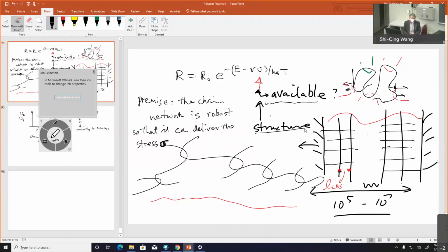So we know we need a high enough molecular weight. We can even throw a word called entanglement there, but it really says little about what entanglement does. I claim here that this chain network is what enables activation. Because in its absence, there will be no molecular mobility delivered, enhanced, as my external deformation starts to take place.